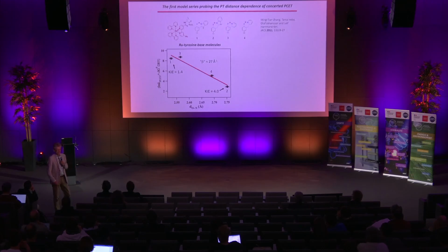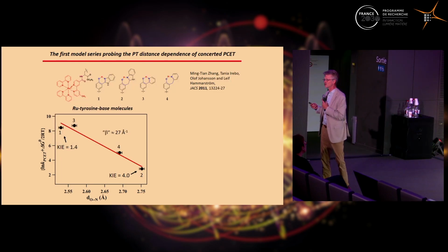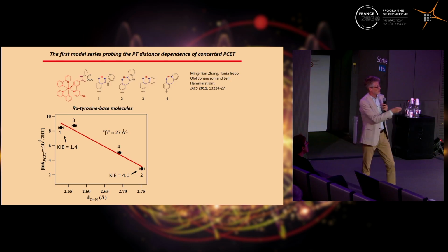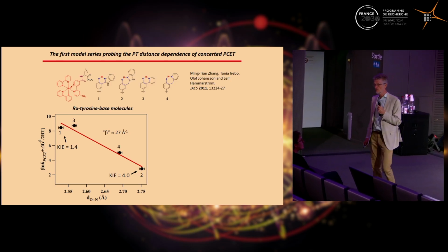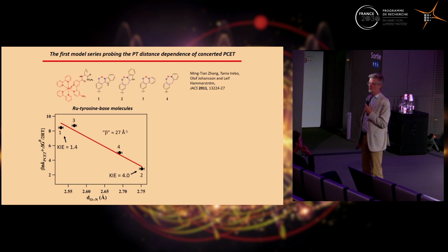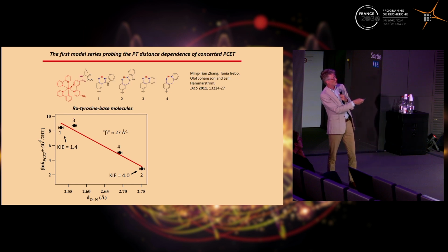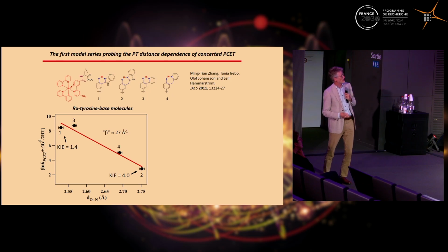Which means that you need to know where you are. Do you have a PCET reaction step? How can I optimize that tunneling? So I've been arguing for 15 years about this thing, that a concerted reaction is really the favorite path. You should really design your catalyst so that the rate determining step is concerted, to have low barrier, and you should also make sure that the tunneling distance is good. And this has become quite popular, to add these second sphere bases, acid-base groups in the vicinity of the metal center to improve catalysis.